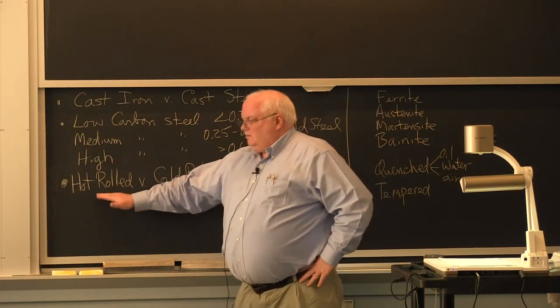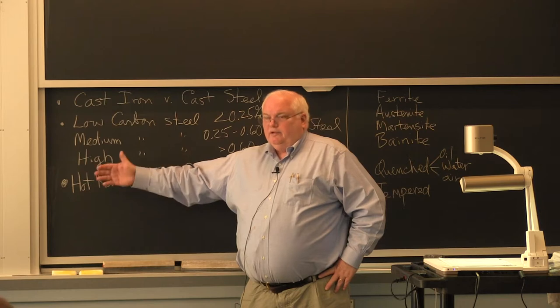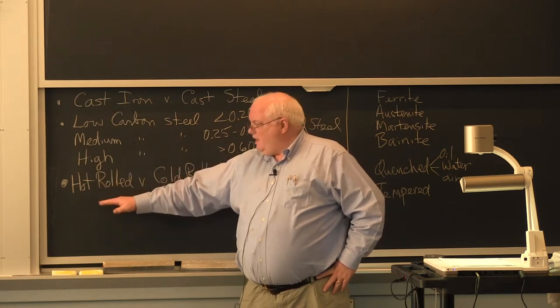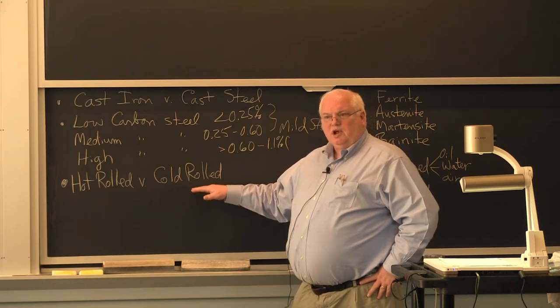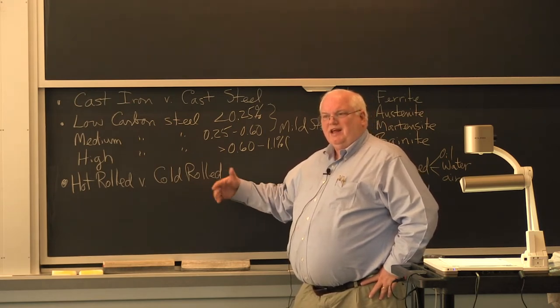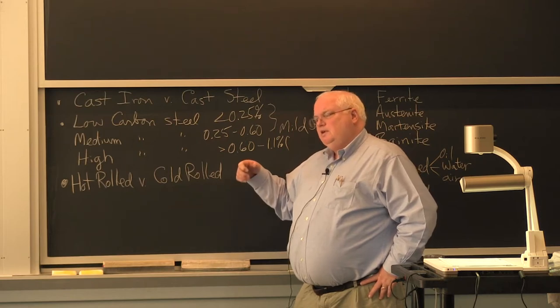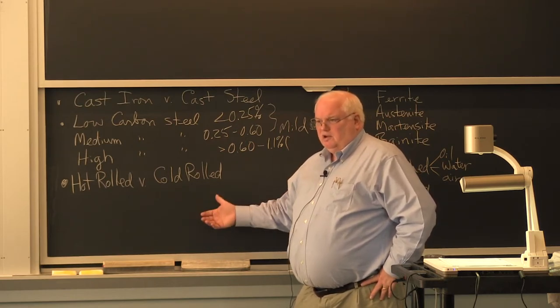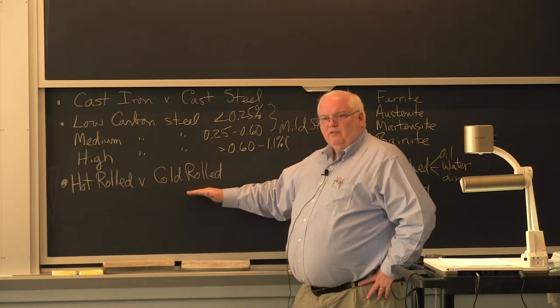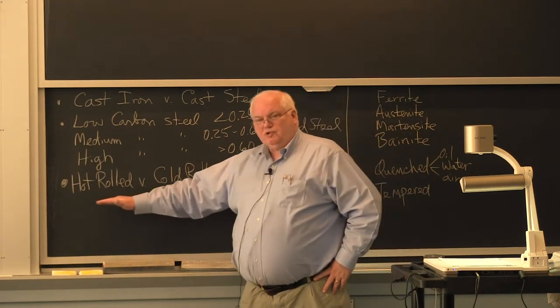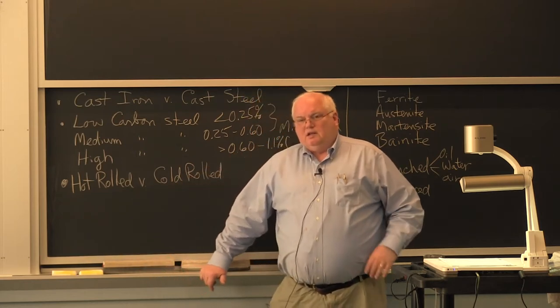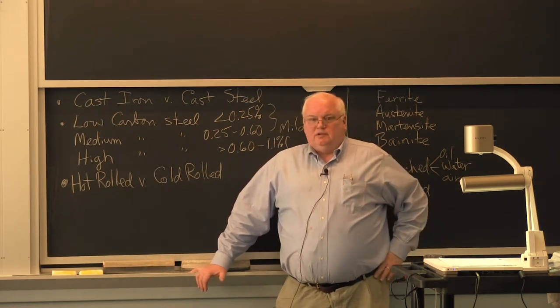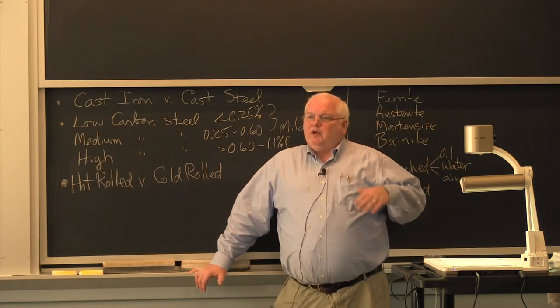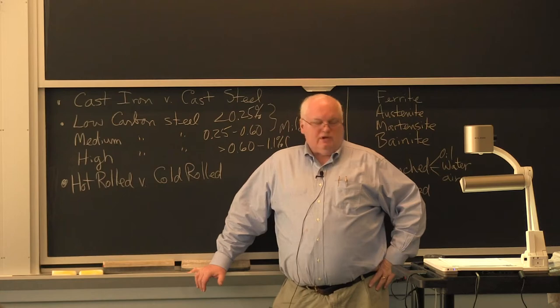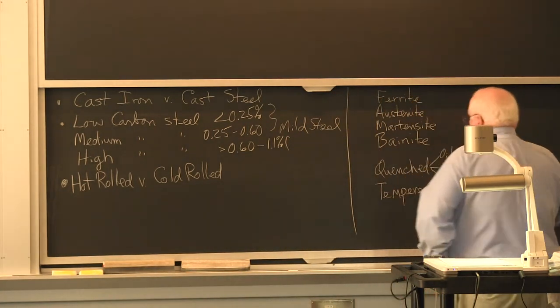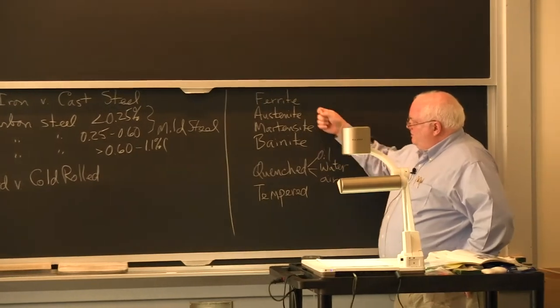Hot rolled comes out annealed, and so the strength is 200 megapascals, 30, 35 KSI. Cold rolled, you can come out with different hardnesses, and we sell it in the annealed condition. We sell it in the half hard condition or the hard condition. You can get 100 KSI out of a low carbon steel in the cold rolled condition, whereas you can only get about 35, one third of that, in the hot roll condition, and it's a function of thickness, okay, coming out of the mill. Now, we can also transform the steel by quenching it and tempering and doing other things, which is what I've written down over here, are some of the other terms.